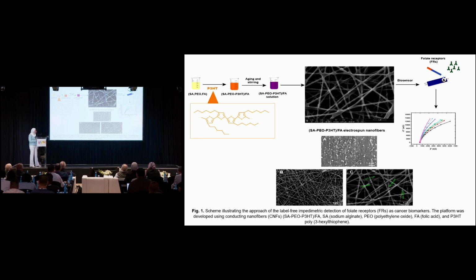Then we deposited the folic acid nanofiber solution on the surface of the working electrode using screen-printed electrodes. Then we incubated with the folate receptors solution in human plasma, and we made detection using the EIS technique, or electrochemical impedance spectroscopy. Here we made characterization using SEM, or scanning electron microscope.